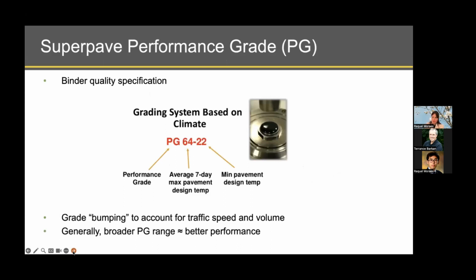Then we went to evaluate the Superpave Performance Grade of the binders. Just to briefly describe what it means, as mentioned when I described the materials utilized in this study, we used a PG64-22 binder. It means that these two specific temperatures are the expected temperatures where that binder will perform well, where the first is the higher temperature the pavement could stand, and the second one is the lowest temperature. When we incorporate additives to the binders, we use a terminology called grade bumping, where we can increase one or two of these temperatures or both simultaneously to target specific traffic and volume. Generally speaking, if the difference between these two numbers is bigger, the better the performance of the binder.